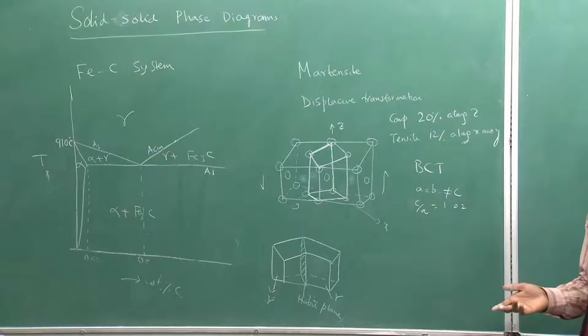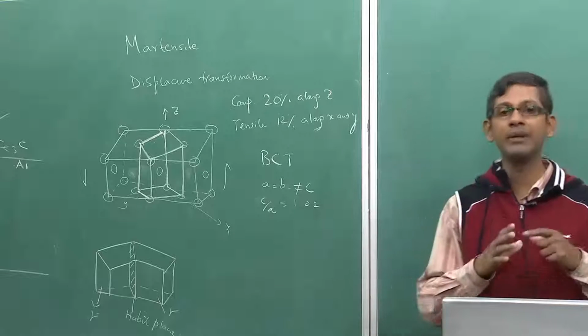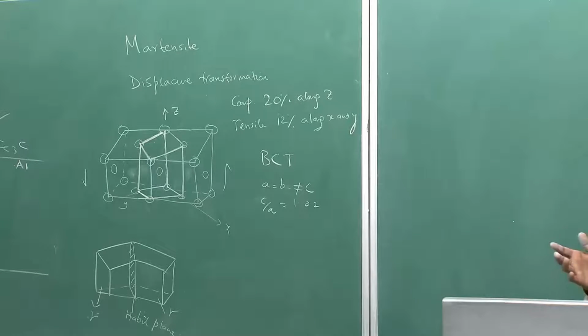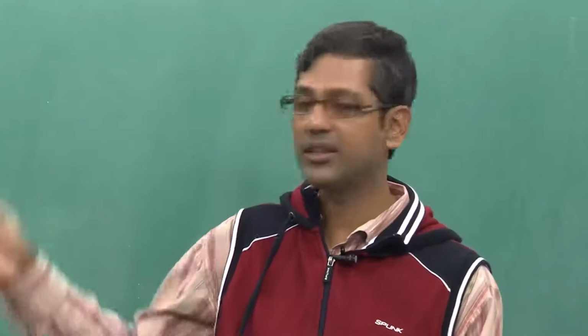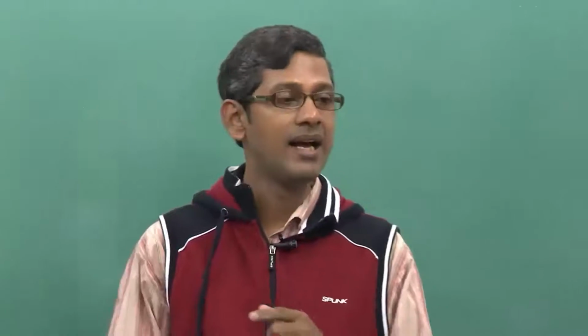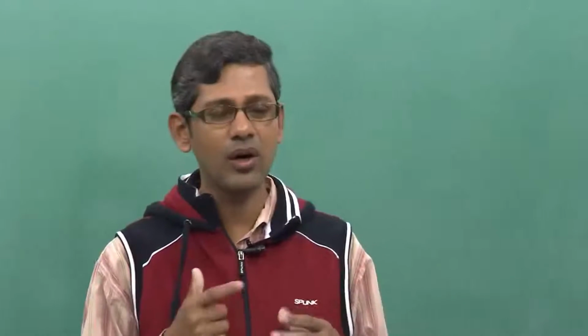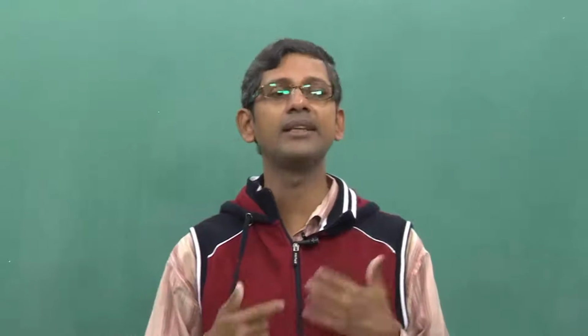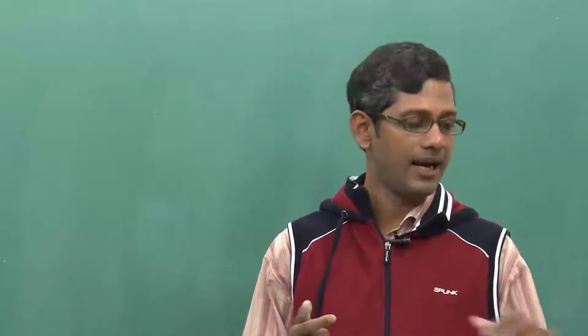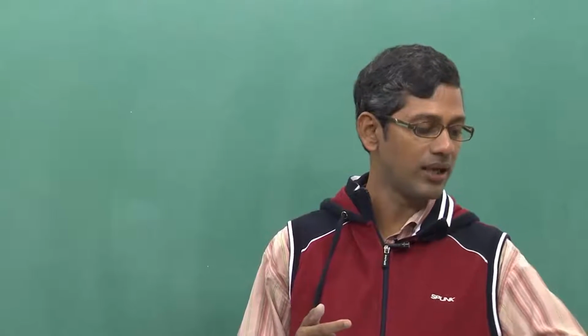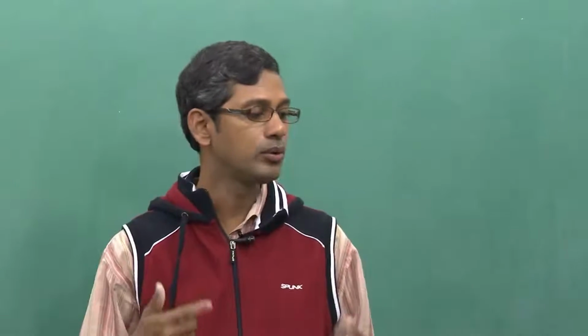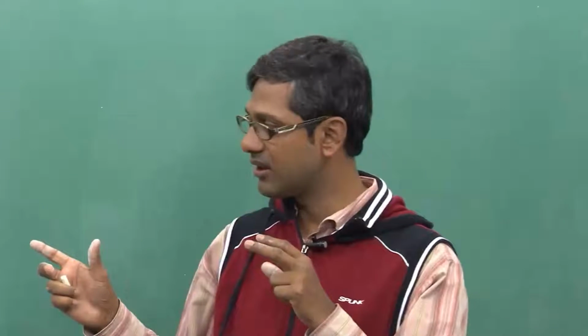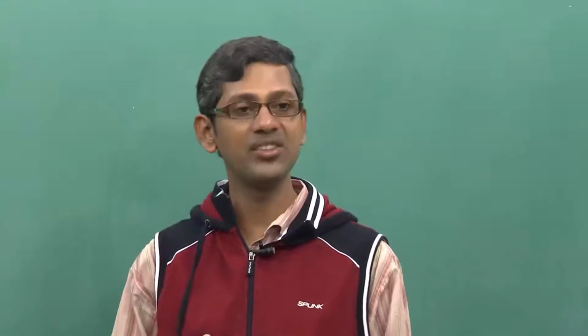How is it possible? That is only possible when strain is applied somewhere else to accommodate the strain because of this plane, and that can be done either by slip or twinning. Although it is very difficult for you to visualize, that actually happens in real steel. To keep these unrotated crystals in the same position, we need to apply slip or twinning.